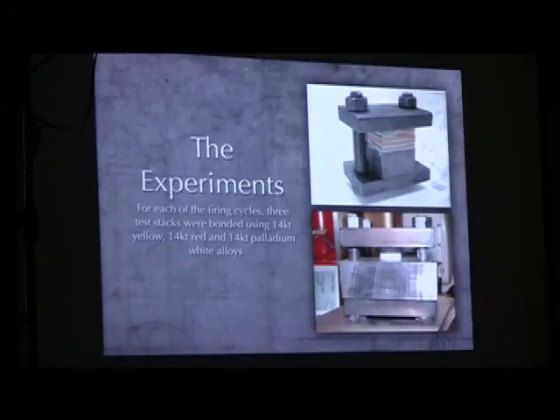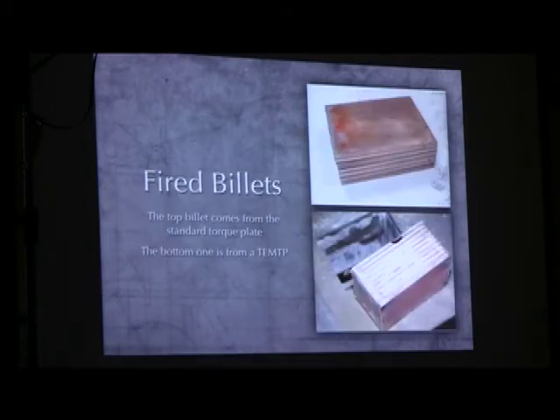And we did a series of experiments with metal supplied by one of the large metal refiners, and they did all the scientific micrographs and things like that to look at our results. But the end result was it worked pretty well. If you look at the top, you can see this is a typical billet fired in torque plates. That's actually a pretty good stacking arrangement. We haven't got too much overhang here and there.